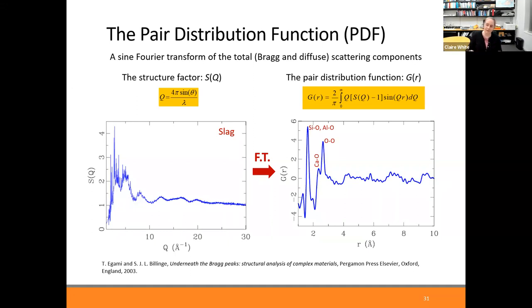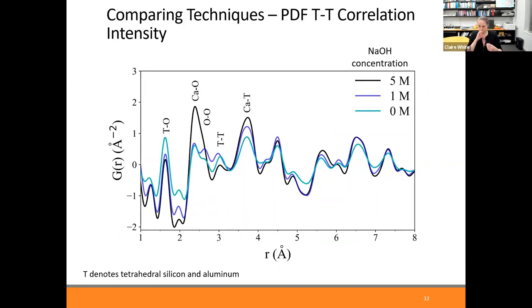So what we're going to do now is look at the data for those gels that we synthesized using X-ray pair distribution function. And that's what's shown on this slide here. And so what we have is bond lengths. T stands for tetrahedral silicon or tetrahedral aluminium. So there's a silicon-oxygen, aluminium-oxygen bond length, calcium-oxygen bond length. And then we look at distances between atoms. We're no longer in the bond length region. And so what you can see is the different concentrations for synthesis do change the amount of calcium that's in the system, but not so much what's going on out in the medium range ordering.